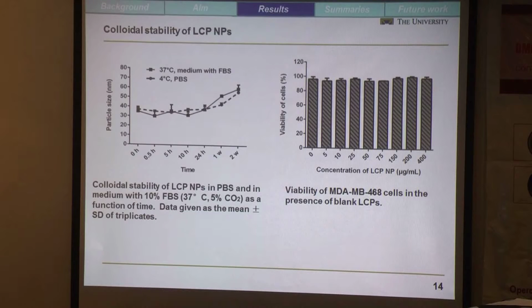So the colloidal stability of the LCP nanoparticles was tested in the 10% serum-containing medium, as well as in PBS at 4 centigrade. As shown in the picture, the LCP nanoparticle can maintain its size range within 24 hours in serum-containing medium, as well as in PBS, even after 1 week in PBS at 4 centigrade. In addition, the cytotoxicity test further confirmed that the blank LCP nanoparticle has low cytotoxicity in vitro within a large